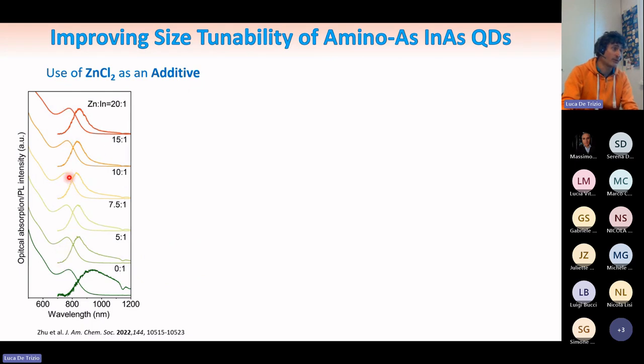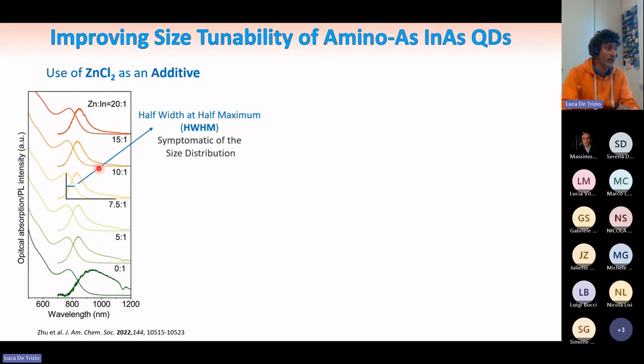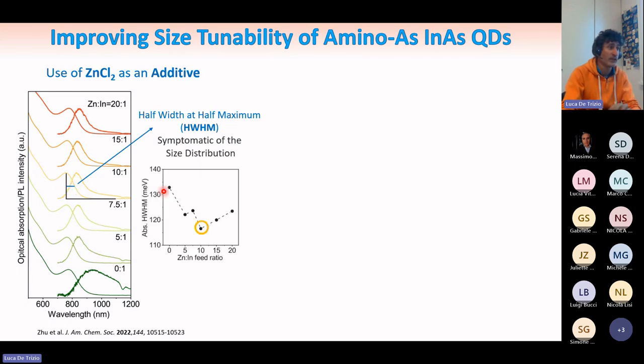From the absorption curves, what we can retrieve is the quality of the sample. That is, if the size distribution is narrow, this absorption curve is narrow. So we can judge this absorption curve to understand if our synthesis was good in terms of size distribution. And if I plot here this width, what you can see is that by increasing the amount of zinc, indeed, we could improve the control over the size distribution.